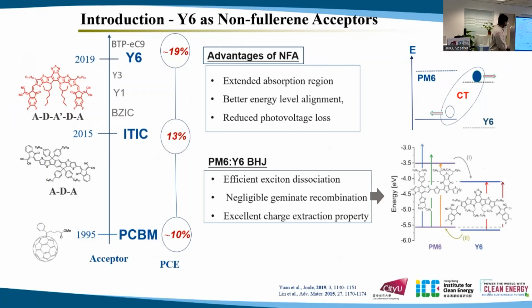It is an A-D-A molecular structure material. And we know that for the last 6 to 7 years, the PCE of organic solar cells is now approaching 20%. It is because of the development of the non-fullerene acceptor called Y6. Compared to fullerene acceptors, non-fullerene acceptors can extend the optical absorption to the near-infrared region. They have better energy alignment with the donor materials and reduce photovoltage loss. And with the popular donor material called PM6, Y6 shows efficient exciton dissociation, negligible geminate recombination, and also excellent charge